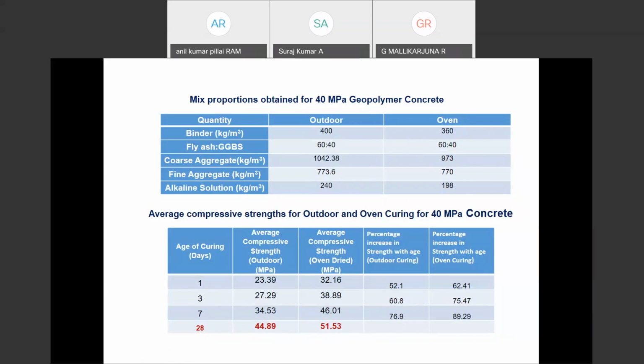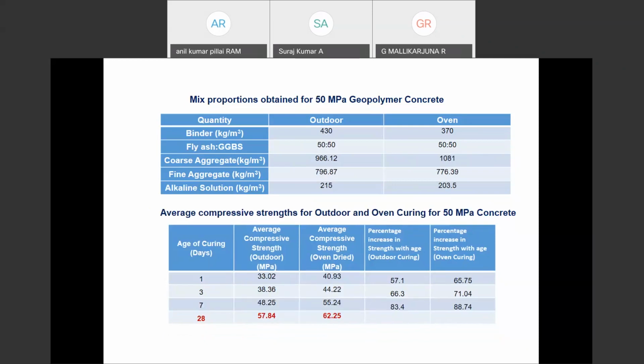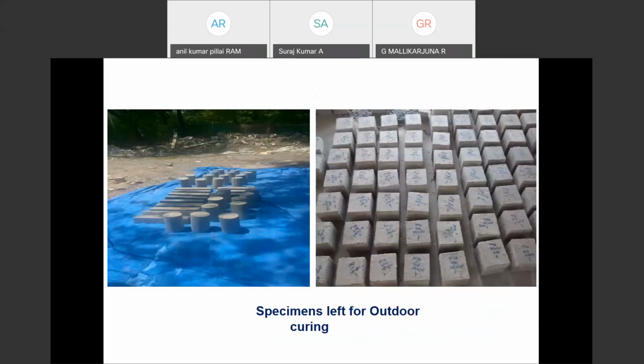And this is the other mix I had selected in order to get the 40 MPa strength. I got almost 44.89 at the age of 28 days. Next I went for 50 MPa. I got the strength as 57. Why? Because after developing all the charts, I had chosen my own mixes and developed the strengths of 20 MPa, 30 MPa, 40 MPa, 50 MPa, and 60 MPa, the required strength.